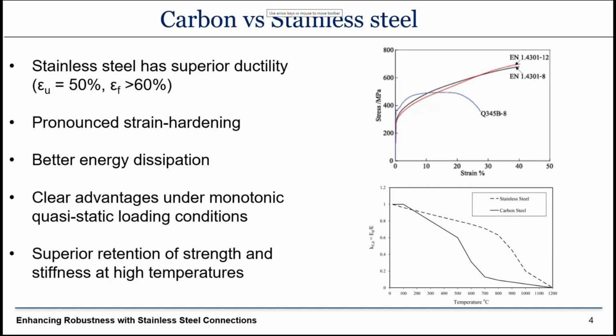Here we can see some experimental stress-strain curves for a typical carbon steel coupon, which is, can you see? You can see my cursor, which is the blue line, and some stainless steel specimens that have overall a lot more strain hardening, a lot higher ductility, and bear in mind we don't show the complete curve here. So some stainless steel grades can have strain at ultimate stress more than 50%, which is a lot more than what carbon steel can have. And they are better in terms of energy dissipation. So there are certain clear advantages under monotonic quasi-static loading.